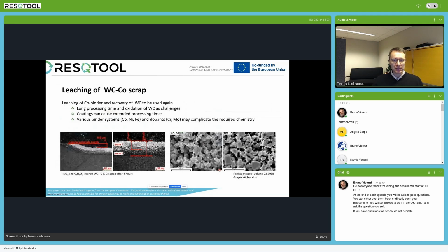Leaching of sintered hard metal scrap. The cobalt binder of the hard metal scrap can be removed. We are using strong acids, and after leaching of the binder, the remaining tungsten carbide mass or powder can be used for the production of new tools. In the leaching of sintered scrap, there are some challenges because the leaching time can be very long due to the long diffusion lengths, and also the tungsten carbide grains may oxidize.